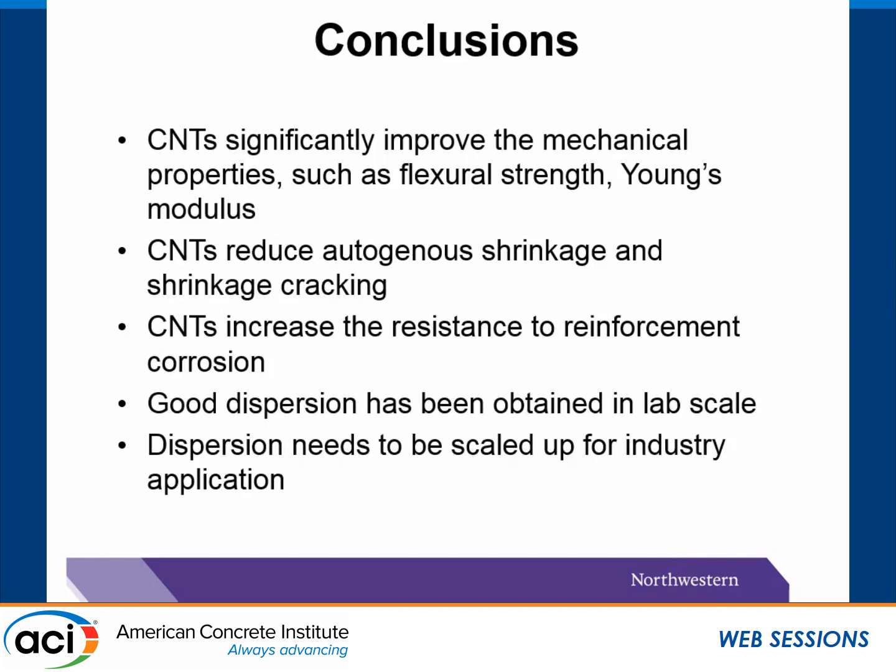Last will be my conclusion of this presentation. First, CNTs can significantly improve mechanical properties such as flexural strength and Young's modulus. Also, CNTs can reduce autogenous shrinkage cracking and increase the resistance to reinforcement corrosion.